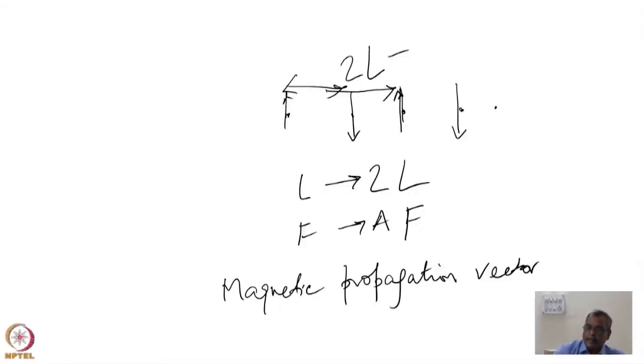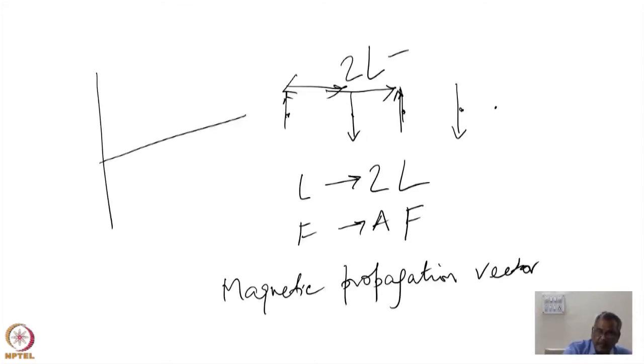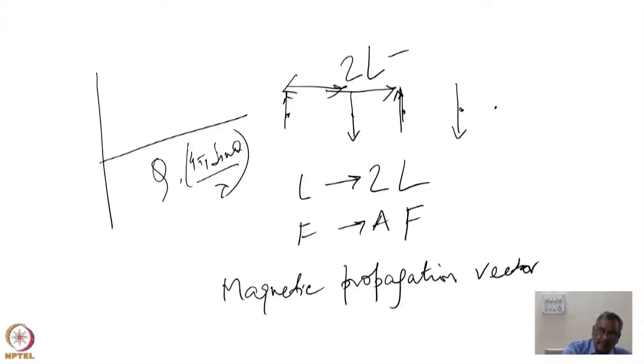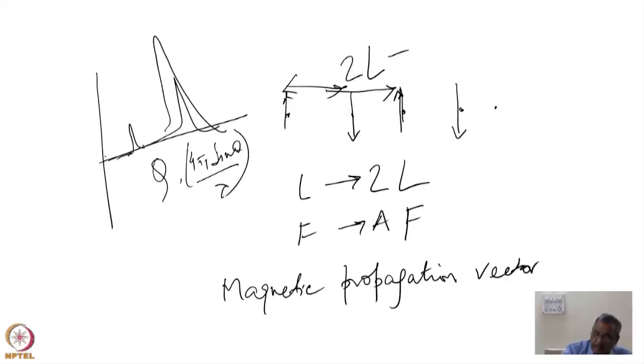As shown in the linear chain example, when going from ferromagnet to antiferromagnet the repeat distance goes from L to 2L. If you look at the intensity as a function of Q (or 4π sinθ/λ), because L goes to 2L the reciprocal lattice vector goes to half. The ferromagnetic peak matches with the crystallographic peak, while the antiferromagnetic peak will appear at approximately half the angle. So a new peak appears when antiferromagnetic order takes place.